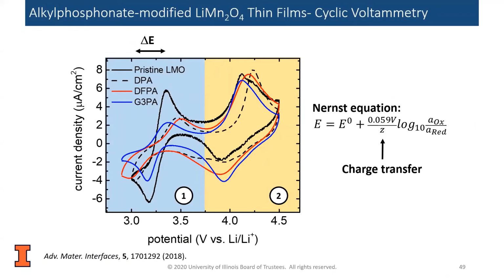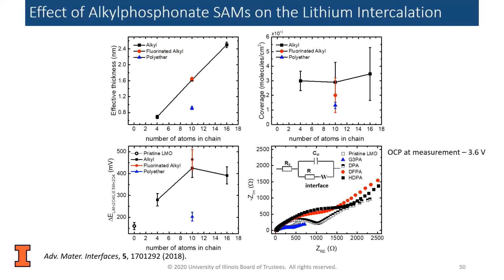And so ferrocene is a fairly large molecule, so we'll actually study the effect of the SAM on the interdiffusion of some larger molecule into the SEI layer. And so in a one electron process, this separation should be 59 millivolts. And so if the charge transfer is reduced, this separation should increase. And so here we are. We're going to now compare the effective thickness of the different SAMs, the alkyl groups, and the fluoro and polyethers.